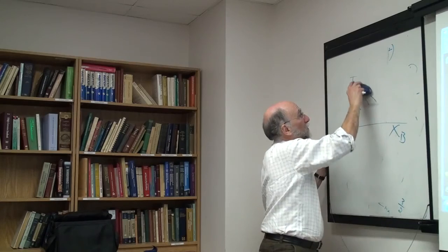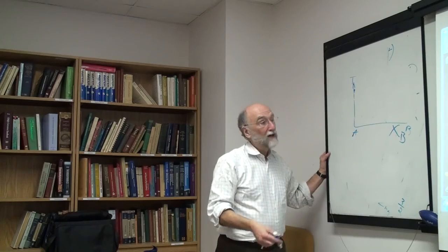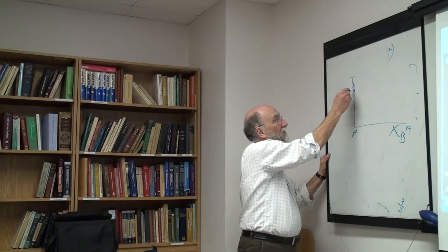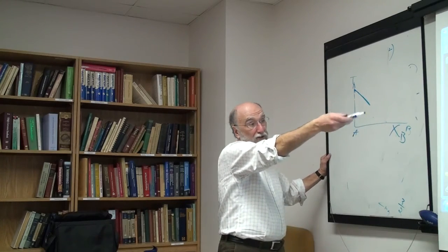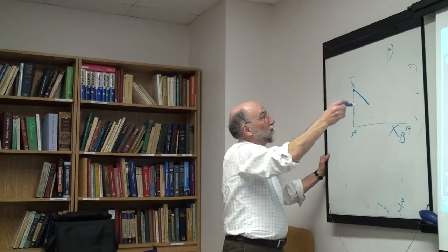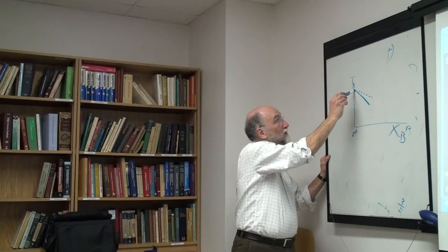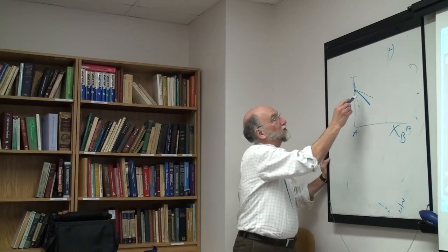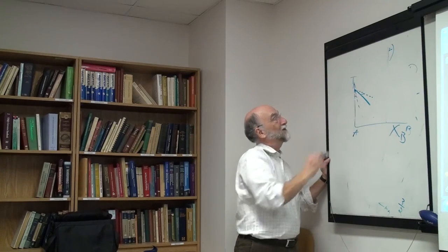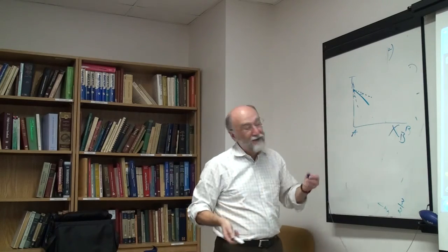Okay, so let's say you have a simple solution, and you know that it's a substitutional solution of two metals. You know the heat of fusion, and the liquidus has been measured like this. This is your measured liquidus. So you calculate your limiting slope equation, knowing the heat of fusion, taking sigma nu to be 1, and you get a limiting slope that's higher, then you know that there must be some solid solubility. If you want to make a very rough approximation, let's just say this distance here is going to be about the same as that distance there. It's not exact; there's no way you're going to exactly work it out. If it was infinitely precise, then you could get it exactly.